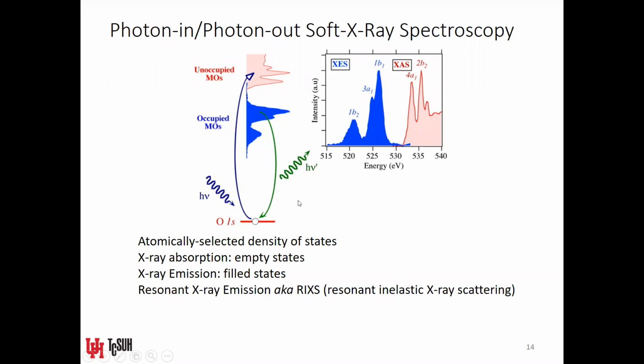So in this case, this schematic is showing an oxygen X-ray emission experiment. Importantly, if you tune the incident photons to an exact absorption edge, then you can resonantly excite an X-ray emission process. And that resonant X-ray emission process not only has the ability to give you a signal that's proportional to the density of states, a kind of band structure, if you will. The resonant form can also give you excitations, because under the resonant condition, various electronic excitations have a higher probability of scattering or occurring, and that can possibly show up in your X-ray emission profile.